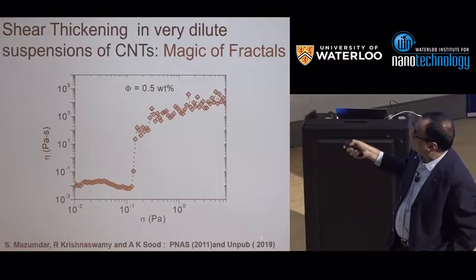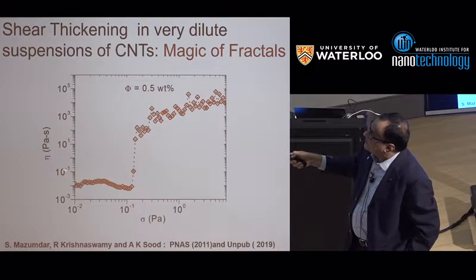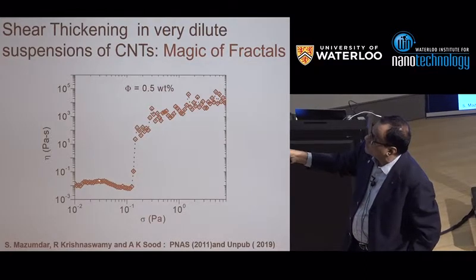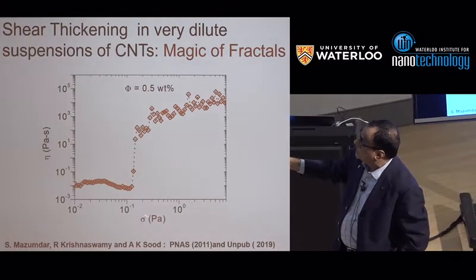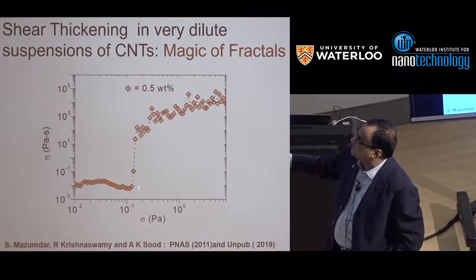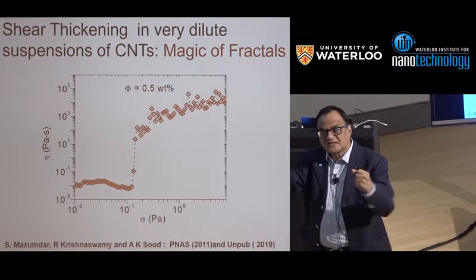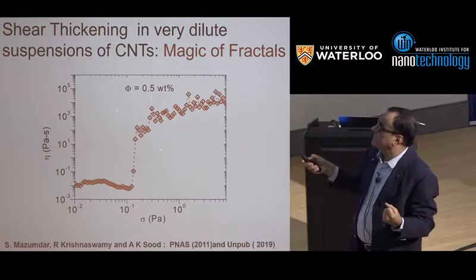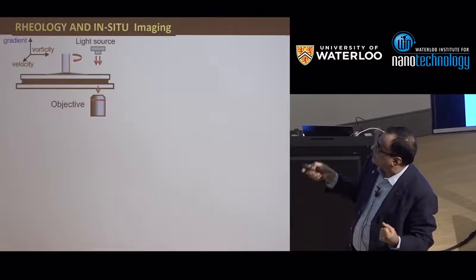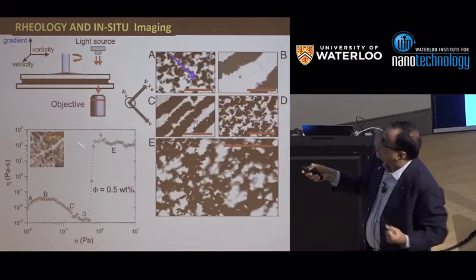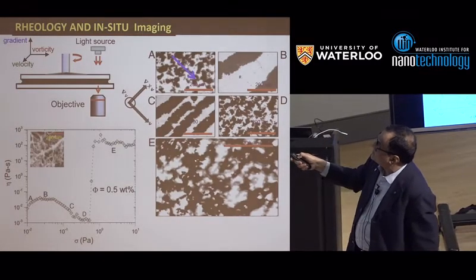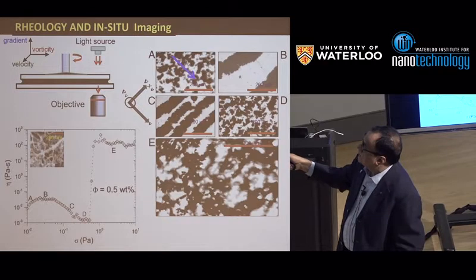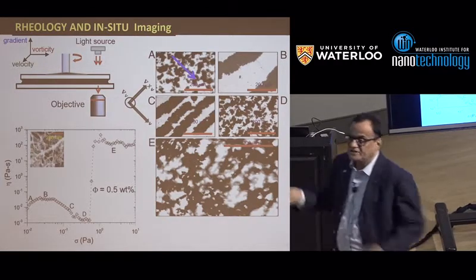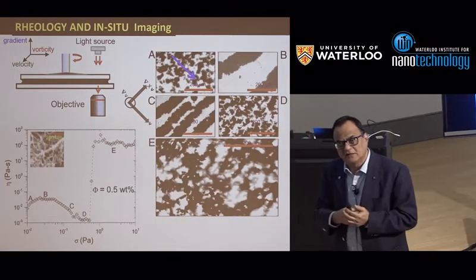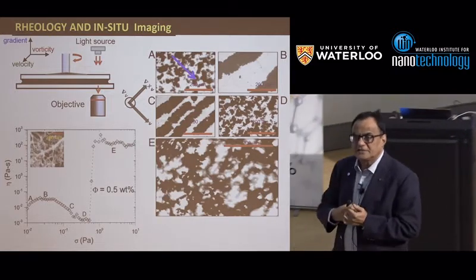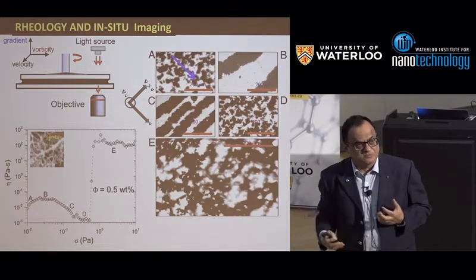And what we showed a few years back, and now continuing with more experiments, is that this viscosity is extremely small, almost close to a few times water, but at high stress, it increases 5 orders of magnitude. So it just cannot move. We understood some of it: at this stage, these are the carbon nanotube fractal flocks, which are really jamming with each other. So this has enormous applications, and the question is, can we extend to other fractal objects and so on.